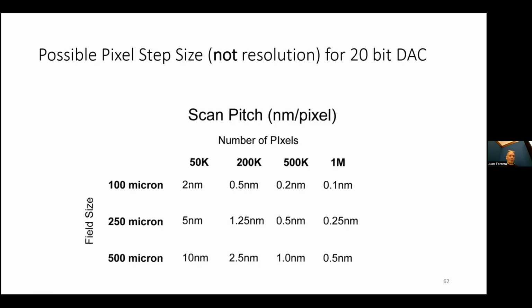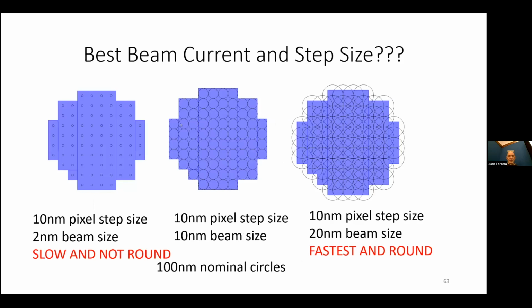And we can pick our different pixel step sizes. I talked about this a little bit before. So if we wanted to use a 2 nanometer beam over here with a 10 nanometer pixel step size, which is kind of the default thing, you might think that's reasonable. But in fact, we very sparsely fill this pattern. We're going to get a lot of line edge roughness. And we're probably not going to get a very continuous dose across here, which is probably not that important. It's going to be slow. It's not going to really be round.